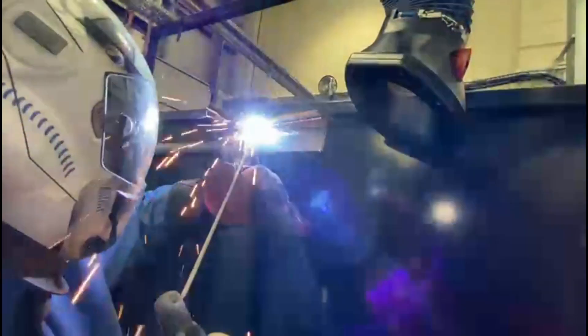With the first run cleaned off, our second run—because we're doing a three-run fillet—we're going to cover three-quarters of the previous run, same kind of angle.